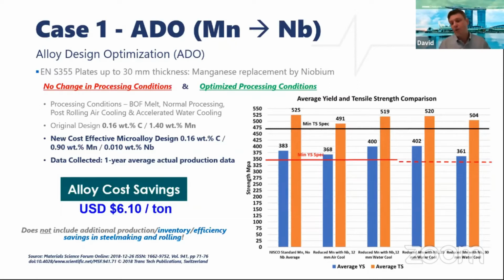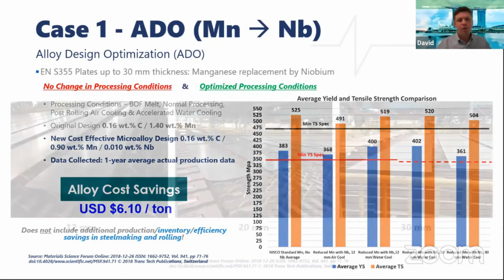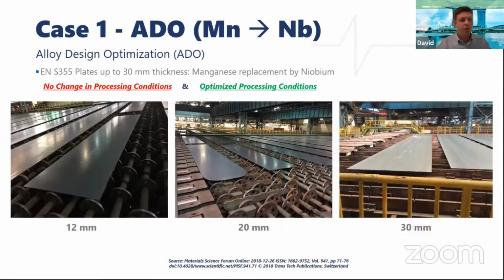As you can see in the bar graphic, the mechanical properties are very, very similar. There was no change in process conditions in the first trials, and we could manage to reduce the manganese even further in following trials, in which we changed the cooling strategy a little bit. But even with air cooling, the mechanical properties were safely achieved, and we could get more than $6 per ton cost reduction by reducing the manganese, and of course, overall, considering the niobium cost as well. As you can see, the plates were very beautiful. There were no problems with flatness or surface or anything. These are also published pictures.